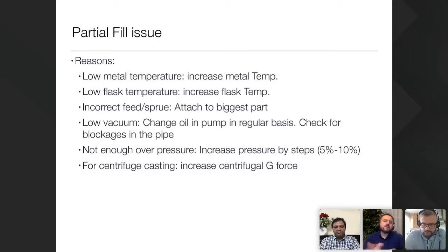One thing is, most of the largest manufacturers all use proper vacuum casting, but I know that in the US or even in some countries, and we did ourselves as well in our R&D, some centrifuge casting. If you have centrifuge casting, what you can do is increase your centrifugal force. Basically, you turn it faster. If you have a higher speed, you will have higher pressure. For vacuum casting, you do that with your casting machine, and you need to have a proper casting machine.